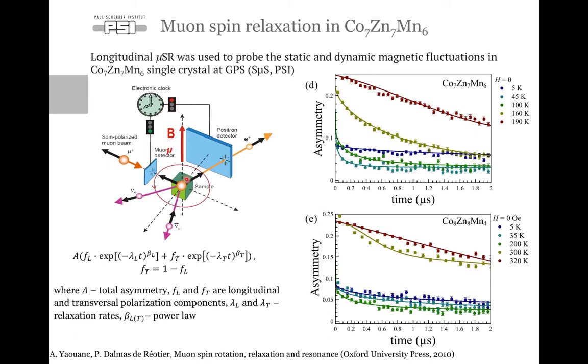So actually at time equals 0, where the muon beam is fully spin polarized and the muon couldn't sense any internal magnetic field inside the sample, the asymmetry of the positron emission is 100%. However, as the muon spin starts to precess in the internal field in our sample, the asymmetry of positron emission changes. And we can measure this asymmetry ratio as a function of time with a time resolution of around 100 nanoseconds.